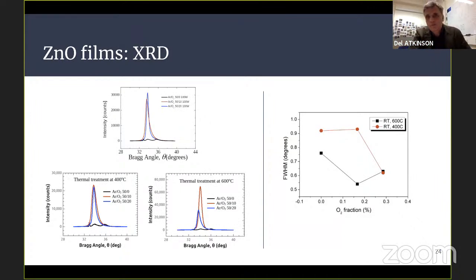Can you speculate? Yeah, I believe that the target we used was a zinc oxide target, in radio frequency magnetron sputtering. When we did the deposition without oxygen, we didn't have the correct orientation. The ZnO was depositing on the substrate in another orientation, another crystalline structure than the 0-0-2 direction, maybe because there was not sufficient oxygen. The oxygen was being lost in the sputtering process. And we may be forming some metallic zinc in some parts. We're not sure, we need to verify. But when we start having oxygen, as expected from literature, we start having this strong orientation in the 0-0-2 direction.